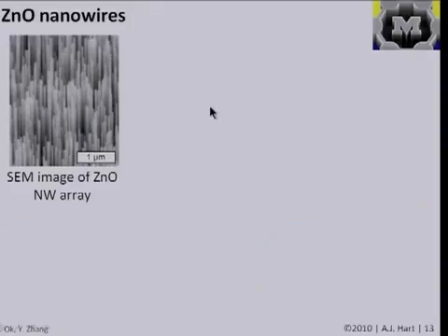So we'll treat a number of examples of different types of structures depending on how much we talk about their properties. So one type of nanostructures that's studied widely are nanostructures or nanocrystals made from zinc oxide. Just when you have it stoichiometric, you have one atom of zinc for every atom of oxygen. And so here's a scanning electron microscope image of an array of zinc oxide nanowires that are grown on a substrate. And when you grow them, as we'll learn later, they grow in a specific vertical orientation because of a relationship between the crystal structure of the zinc oxide and the crystal structure of the substrate. In this case, these were grown on a particular orientation of single crystal sapphire, or Al2O3.